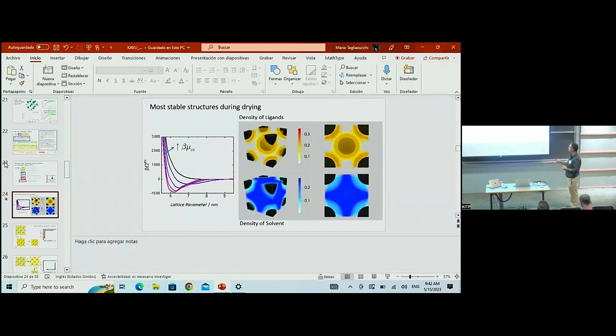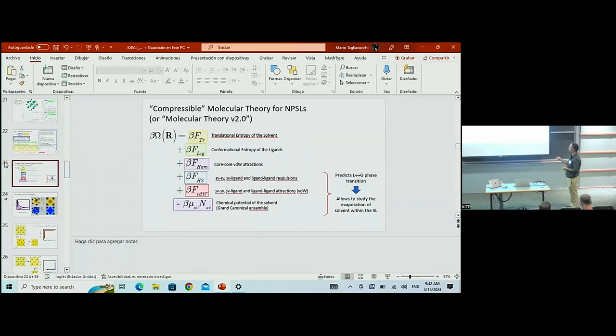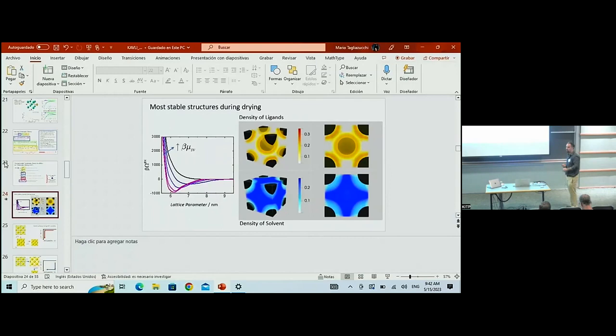Regarding the energy scale, it may have to do with how we choose the interaction parameters. This van der Waals interaction has an epsilon value, and we pick that in order to have a liquid just a little bit below the critical temperature, so we do have a liquid-gas transition. Maybe we pick it too far below the critical temperature. But still, the order of magnitude is not that far away from what you know from simulation. So I think it's not bad.